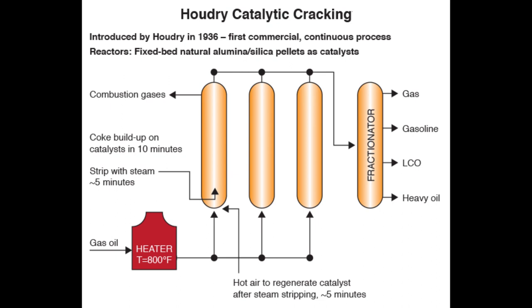That's essentially the cycle in the Houdry cat cracking process — enabling a continuous flow system while the reactors are taken out of service for decoking operations. The endothermic reaction of cracking is decoupled from the exothermic reaction of burning the coke. For that reason, the thermal efficiency of Houdry cat cracking is not very high, and it certainly needs to be improved.